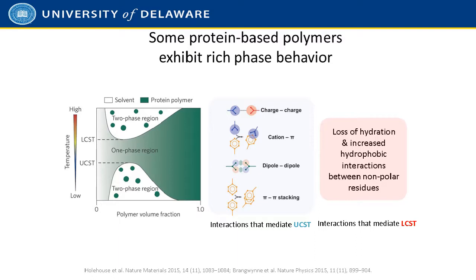If one progresses out of this green shaded area to lower temperatures, so down in this graph, one traverses the upper critical solution temperature, or the UCST. That phase transition is controlled by a range of dipolar type interactions in the polypeptide chain. And because we can engineer and specify where specific chemical groups are located on the chain, that gives us a great deal of flexibility in controlling the temperature at which this phase separation happens.